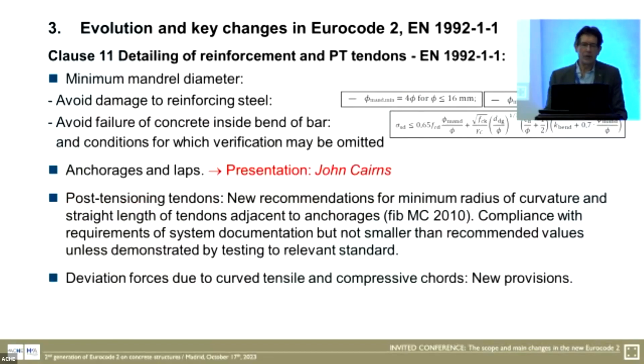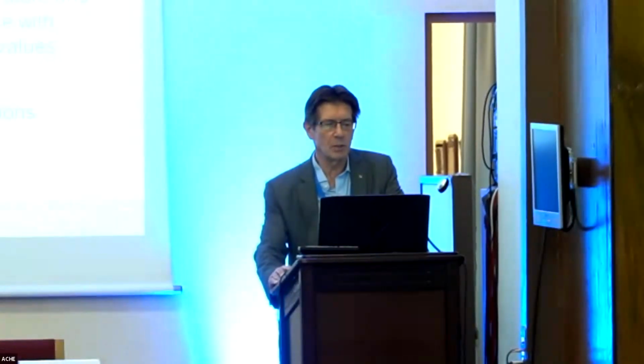Clause 11, detailing of reinforcement. A few words about minimum mandrel diameters to avoid damage to reinforcing steel. No change, that's what we have today, but we introduced some new provisions to avoid damage to the concrete inside the bends of bars. We give conditions where no such check is needed, and that covers many or most of the cases in practice. But for special cases where you need to check, we give a detailed formula here, which allows you to make sure that you do not crush the concrete inside tight bends. The main part of clause 11 will be presented in a separate part, and then at the end of clause 11, we have some additional provisions for post-tensioning tendons and deviation forces due to curved tensile and compressive chords.